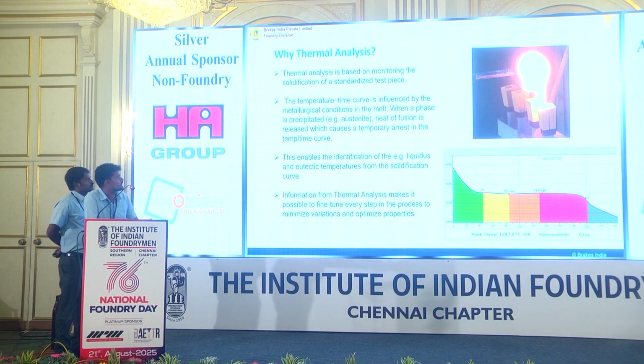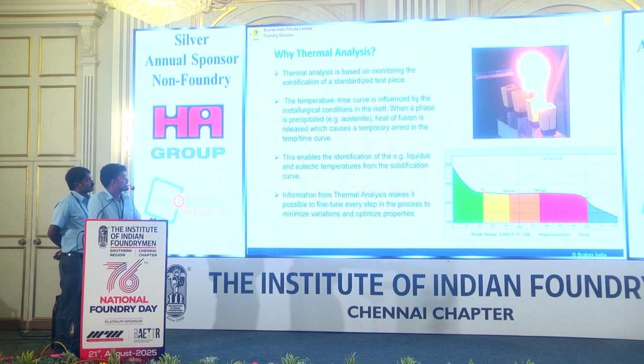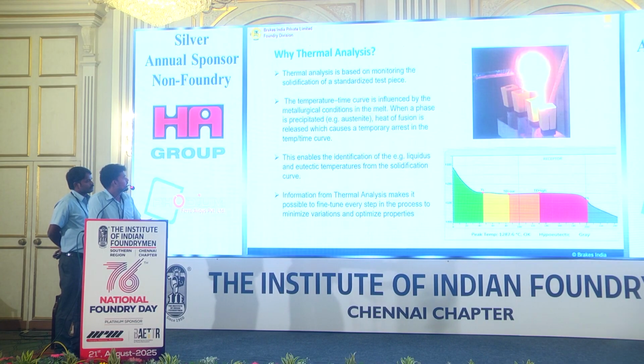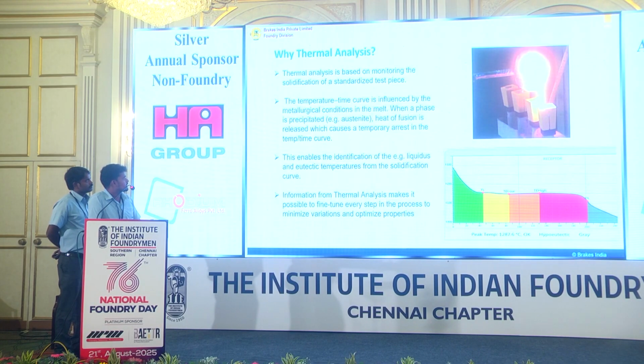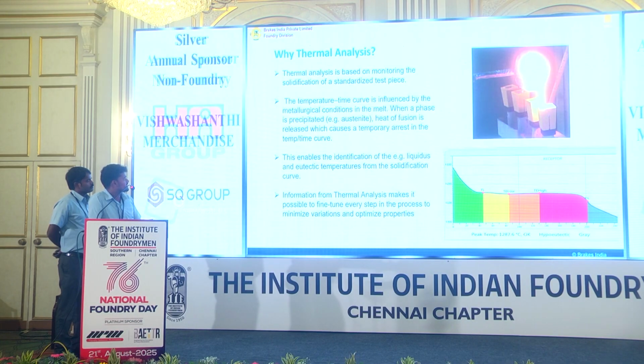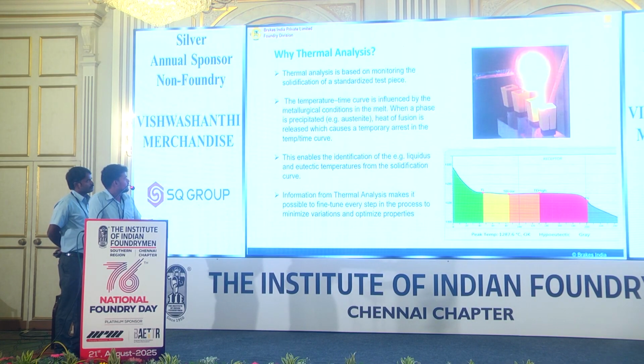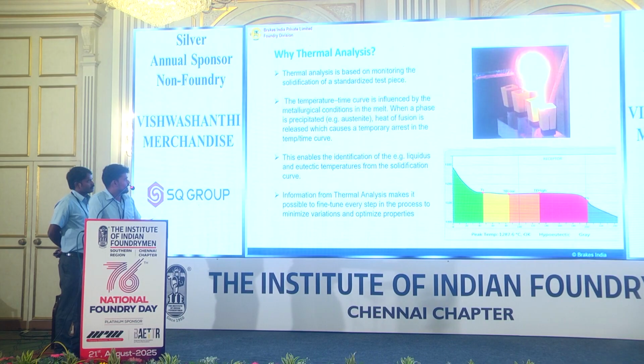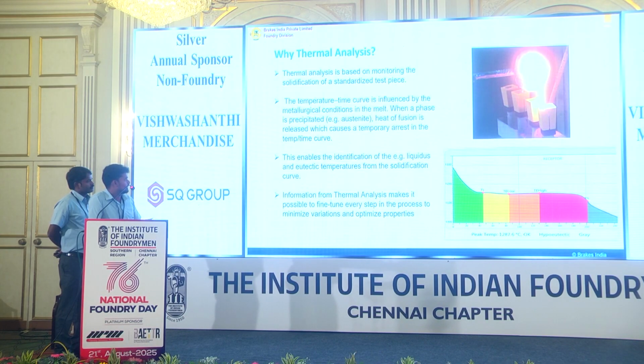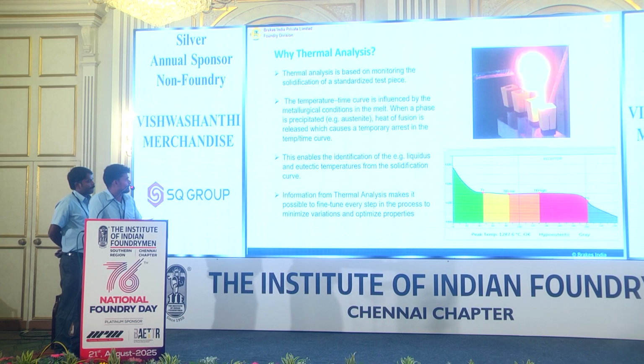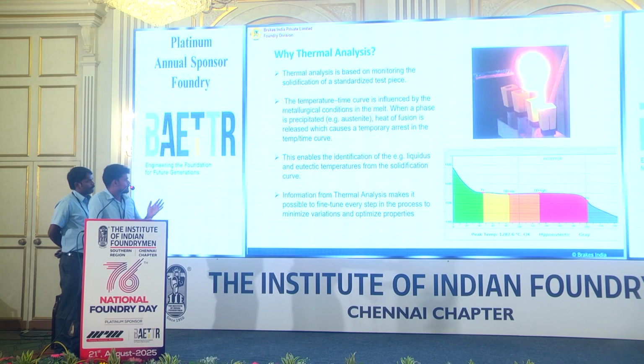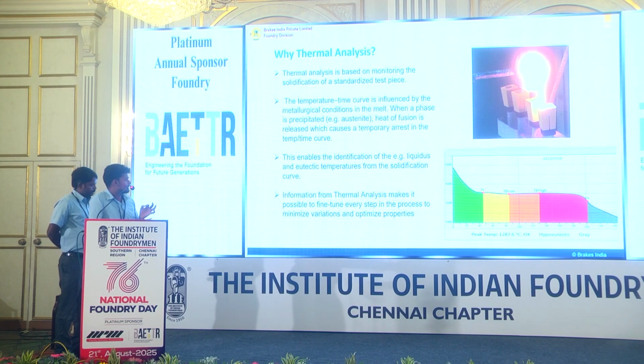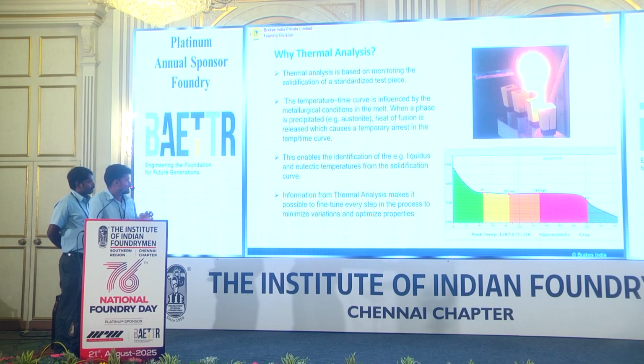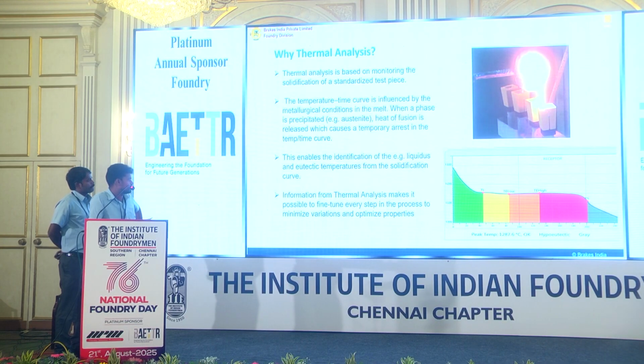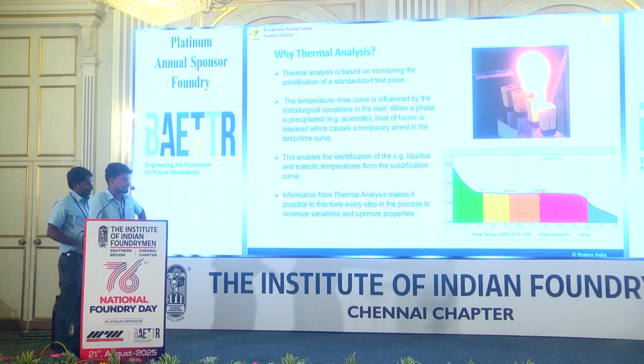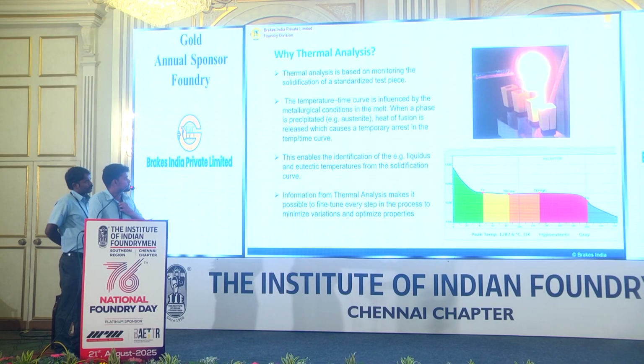Thermal analysis is based on monitoring the solidification of a standardized test piece. It gives the time temperature curve. It is influenced by the metallurgical conditions in the melt. This enables identification of liquidus temperature and eutectic temperature from the solidification curve. So the information from thermal analysis makes it possible to fine tune every step in the process to minimize the variation and optimize the properties.